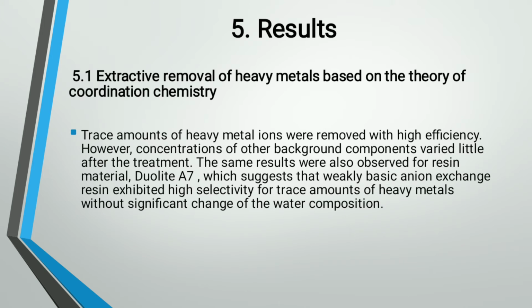Let's move to the results. The first result was extractive removal of heavy metals based on the theory of coordination chemistry. Trace amounts of heavy metal ions were removed with high efficiency. However, the concentrations of other background components were little changed after treatment. The same results were also observed for resin material Duolite A7, which suggests that weakly basic anion exchange resin exhibited high selectivity for trace amounts of heavy metals without significant change of the water composition.